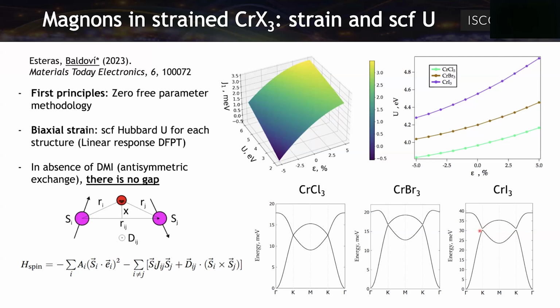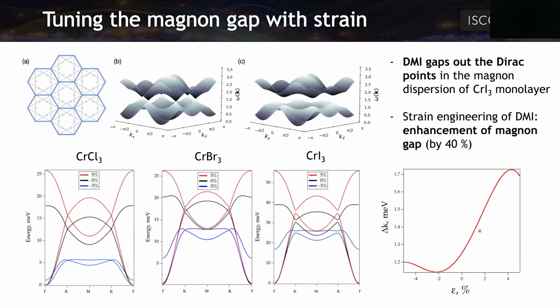So with this, we can predict, following a full ab initio approach, that this opening of the gap comes from the Dzyaloshinskii-Moriya interaction, and then we can tune it with a strain, like biaxial strain. We can observe how the structure is evolving, and if we apply 5% of strain, we are increasing this gap. This is compression, this is expansion, and with this expansion we are tuning directly the Dzyaloshinskii-Moriya interaction, and we can reach a higher value of this magnon gap. This is the value that we obtain fully ab initio, being more or less twice the value of the real magnon gap determined by inelastic neutron scattering.